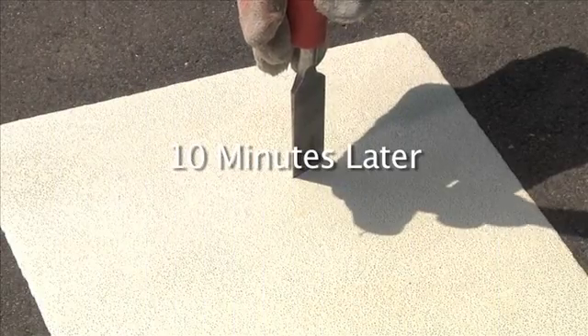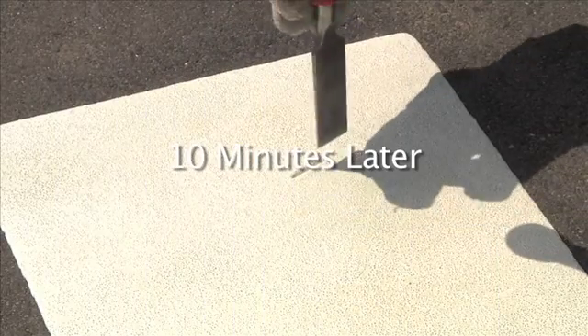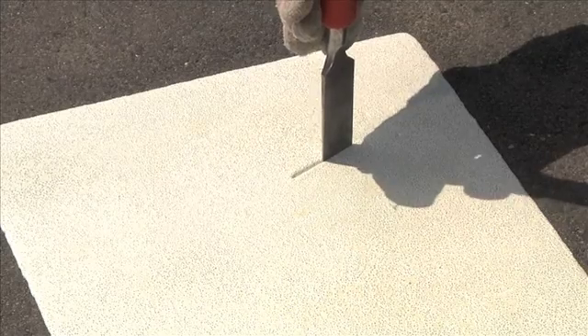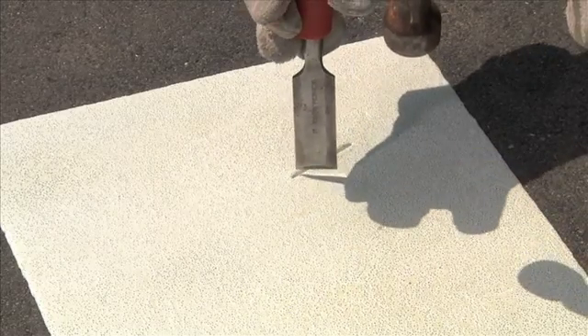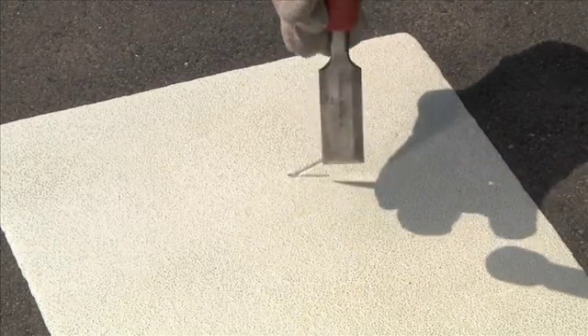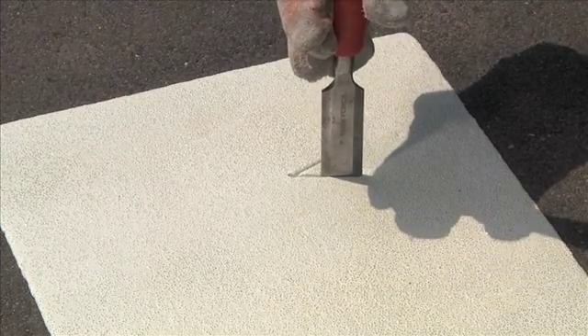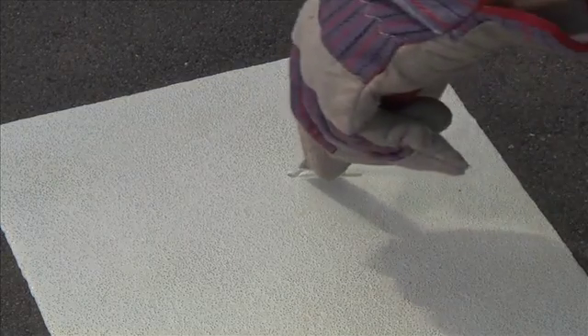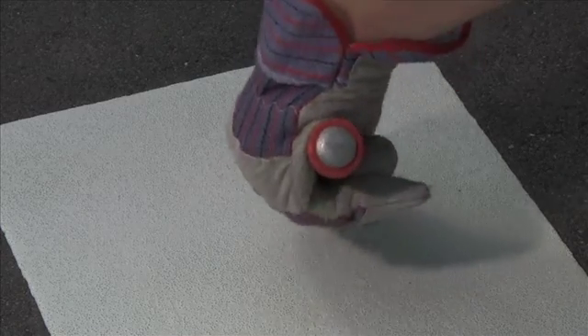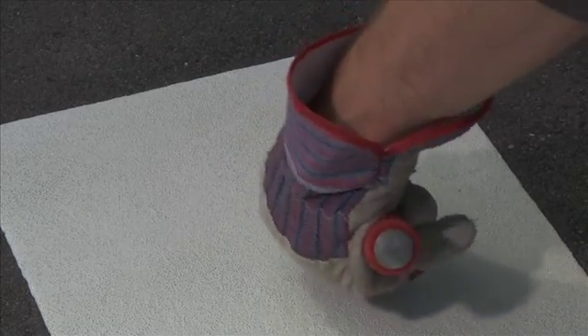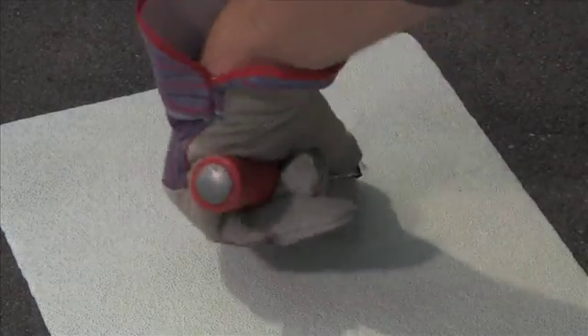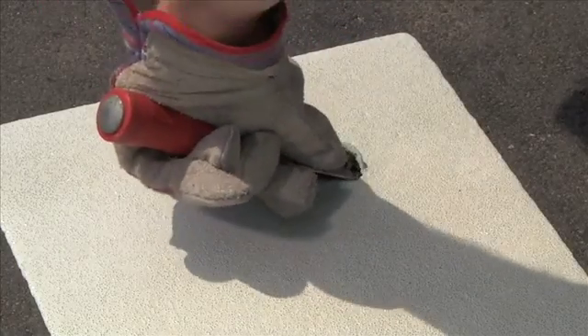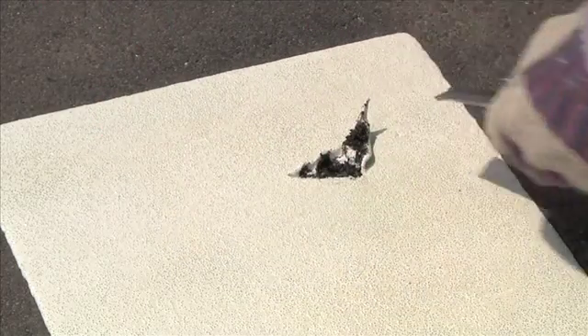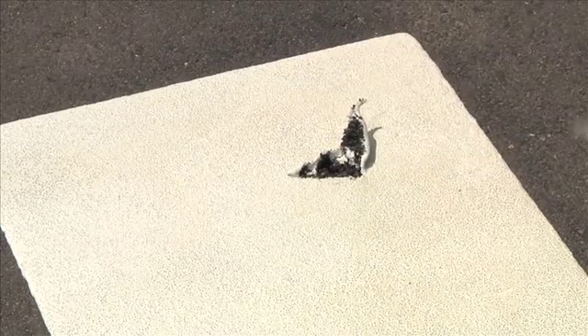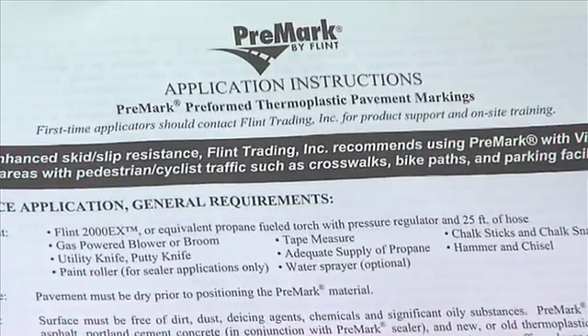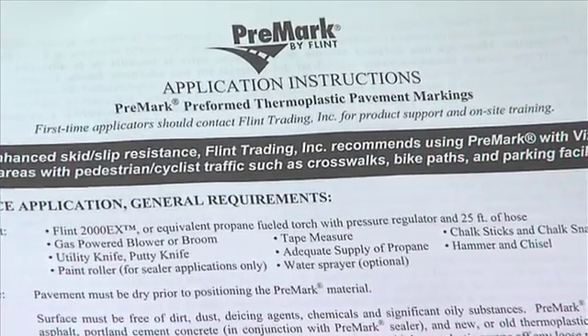We will now perform the chisel test by cutting a small area of material and pulling back to verify proper bond. As you see here, a solid bond has occurred because aggregate is evident on the underside of the material. Furthermore, the glass bead embedment is satisfactory as well. We trust these application demonstrations will help you understand the distinct purpose of dividing preformed thermoplastic pavement marking materials into two types, preheat and no preheat. Optimal performance can be achieved using either product by following the specific application instructions provided with each product.